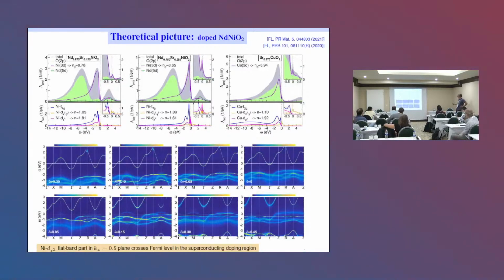So this is a busy slide, but we did the calculation for the cuprate in the overdoped regime, and we see this sunrise-like thing. The greenish thing, the quasi-particle, is composed of two kinds, copper d and oxygen. Both have the same contribution, whereas it's quite different for the same level of doping for the nickelate. And that is understandable because, as we said, it's not charge transfer-like, it's more Hubbard-like. So the oxygen has a contribution, of course. It's not black and white, but it doesn't have a large contribution.